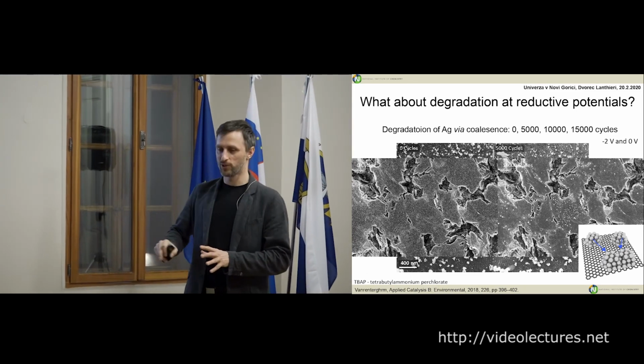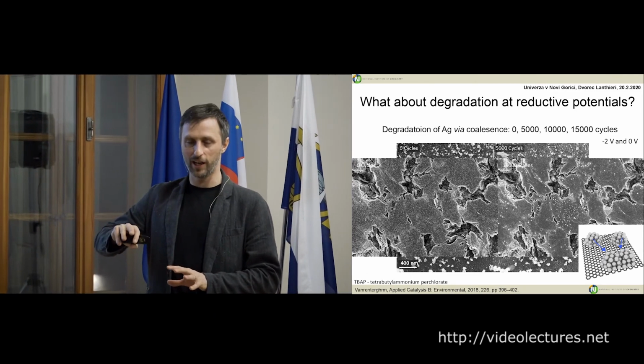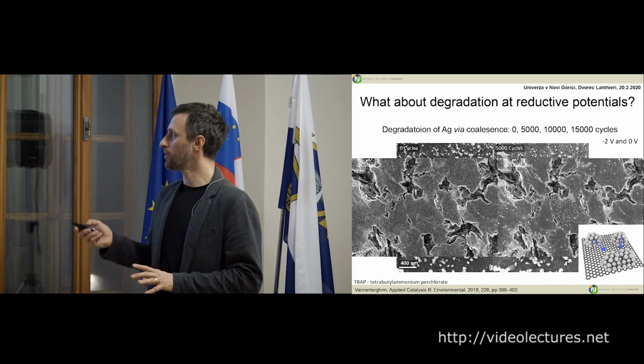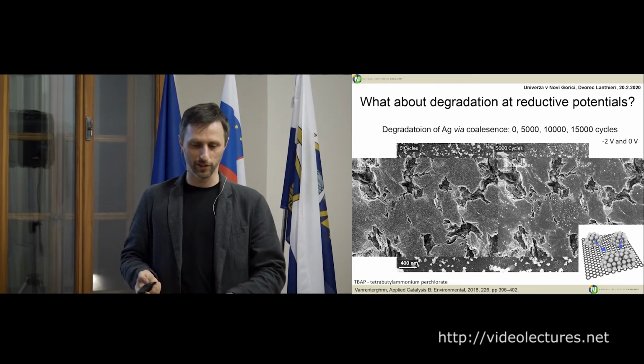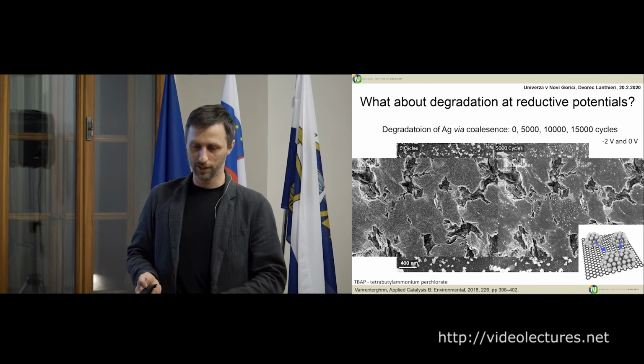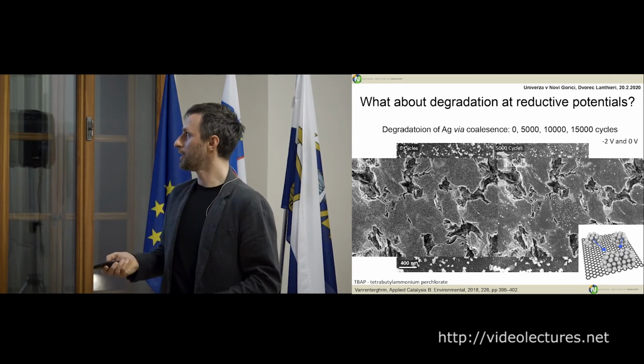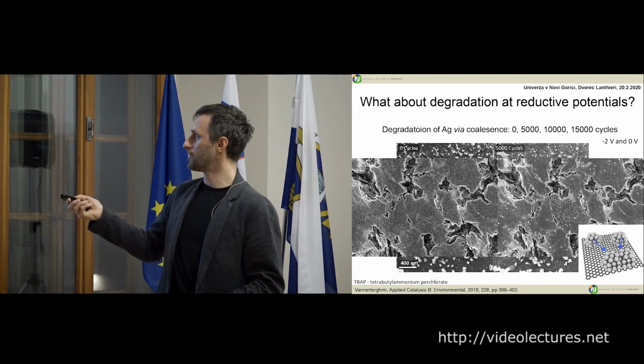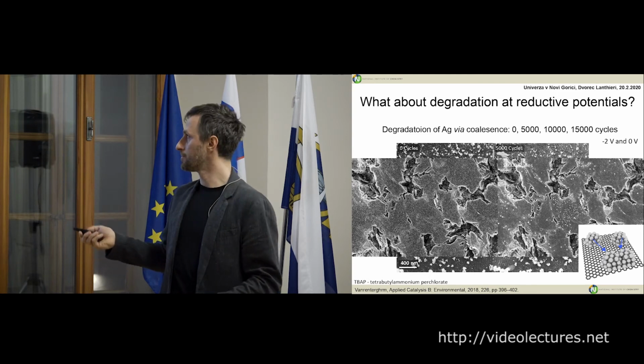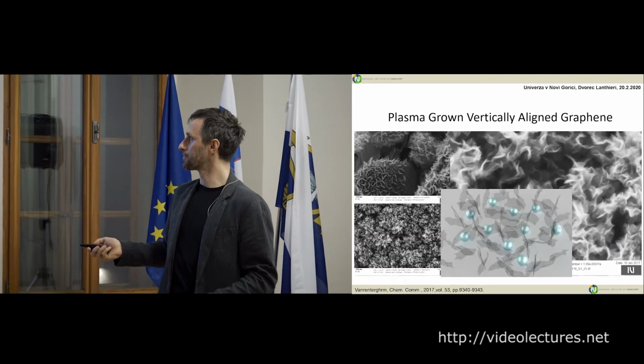So this was all degradation at higher potentials. Now, what's happening in the negative potentials, when you go to the hydrogen side, to the other side? Here you can see at this identical location, you can see coalescence. So coalescence is this mechanism.